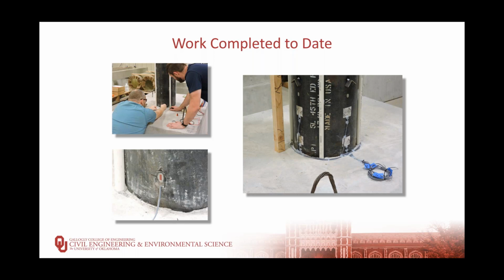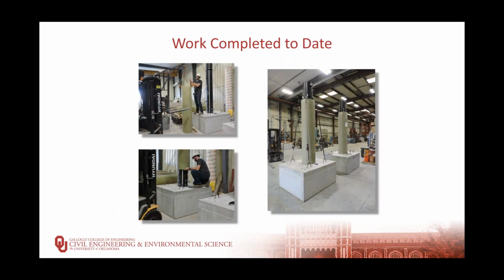Once those strain gauges were installed, we were able to lower the FRP tubes into place, make sure that they were centered around the steel tubes, and then secure them in place with a halo at the top and the braces. This would allow us to place the concrete without disturbing or moving the FRP shell to complete the construction of the column.